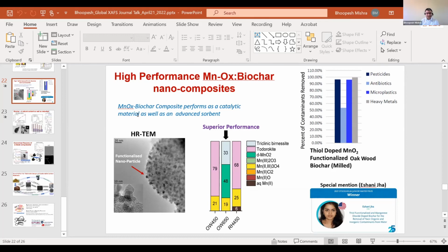But more importantly, what also happened in the meantime is that, not completely accidentally, because we wanted to test that anyway, we also realized that this material is actually very good in water purification, because you see that it not only takes away a plethora of heavy metals, including cadmium, mercury, lead, and arsenic, but also does a very good job with microplastics. And that is likely because manganese oxides are also breaking down microplastics and pesticides. Not so well with antibiotics, but that's okay. It's still 50%.